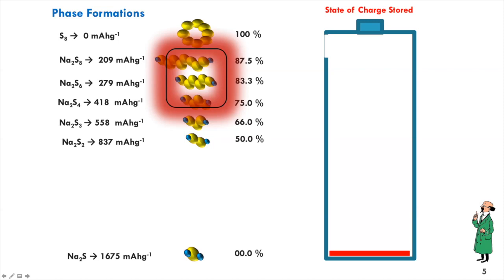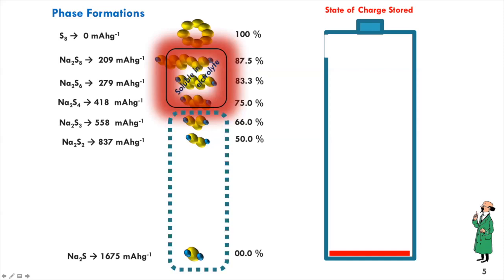But when you want to extract more and more, if you add more and more lithium and sodium, because most of the people are interested to have more than, let's say, 1000, 1675 is the theoretical capacity. If you exchange all the sodium along with it, it goes through phase transitions. And here, the last phase is a solid, and before that these are polysulfides, which are soluble in the electrolyte.